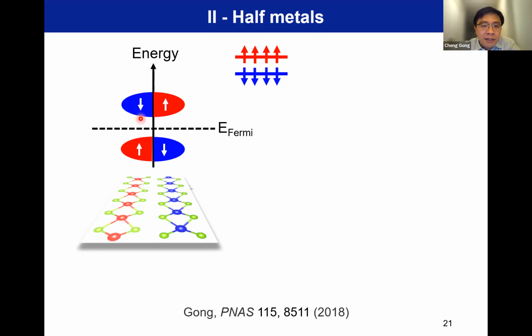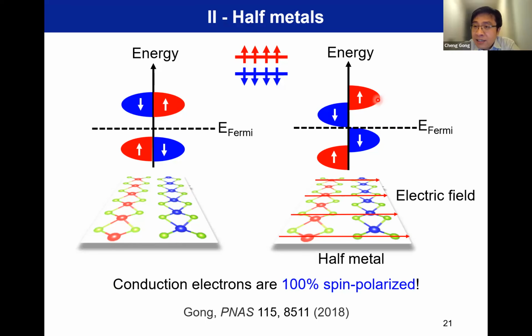You have the spin up and spin down band splitting in the two layers in a reverse way. So you can imagine now, if you apply an electric field across these two layers, the two layers will feel different electrostatic energy, right? They have different potential. So you will lift up the energy level in one layer, and push down the energy level in the other layer relatively. So in the end, you will merge one spin polarized band and open up the spin polarized band of the other spin. If you flip the electric field, you can push the red band here to be merged at the Fermi level and the blue band be opened. So anyhow, you can see we form a special material that's called half metal.